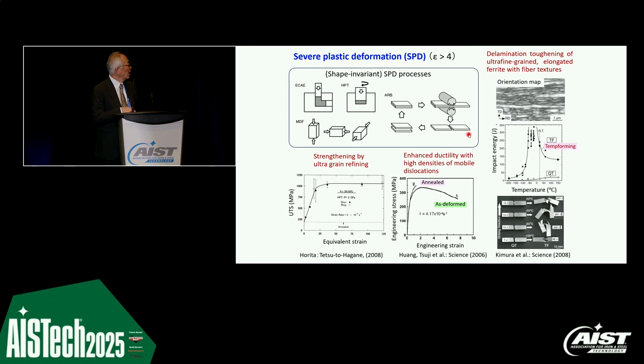The other case is caliber rolling, where they apply severe plastic deformation. And in this case, we get ultrafine grain fibers and texture. Then, going down to low testing temperature, we actually have an increase in toughness. This is called delamination toughening: along the longitudinal direction, we have the preferred fracture. However, it is difficult to penetrate such cracks over the thickness. So that's why we have this very peculiar phenomena in toughening.